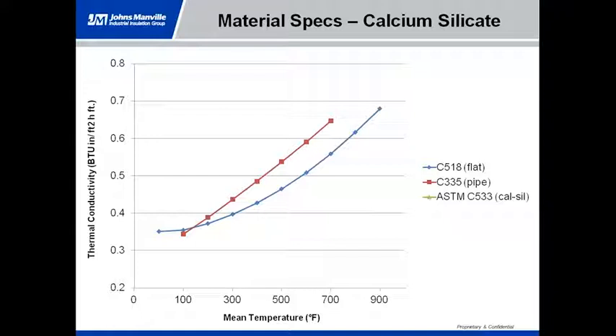But at 300 degrees, we see that things start to change a little bit. And again, we also notice that the pipe testing is translated up. So again, a higher value means we're going to have more heat loss than we're going to have with a lower value. Okay, and finally, this green line on top, this is what the ASTM standard specification requires for calcium silicate products. And again, note that it tends to parallel the pipe testing data.